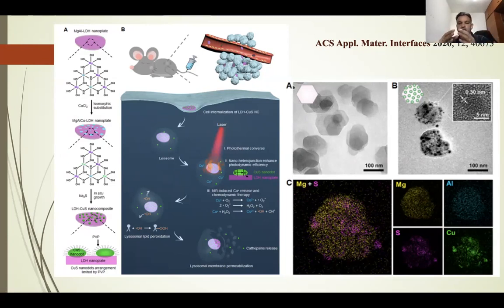fabricate, or we try to generate nanoparticles on the surface of the material by using this PVP to control the size of the nanodots. So these nanodots can help in photothermal conversion, as well as this copper sulfide could create as many free radicals as possible. This is one way, and photothermal is another way. So by these two, PTT as well as CDT, chemodynamic as well as photothermal, could subsequently demonstrate the cancer efficacy, where the copper sulfide loading is confirmed by EDS map.